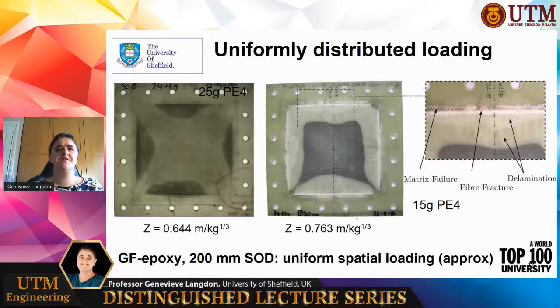And even though these are both still near field tests because the Z value is below one, it's approaching the far field pressure time history. So it would have been loaded for a longer time and over more of the area of the panel. We see far less fiber fracture. We see some of the failures along the clamped boundary that I was talking about before. So instead of having the failure in the middle of the panel, like you do for a very localized test with a small standoff distance, you're then getting these more uniform failures across the panel.